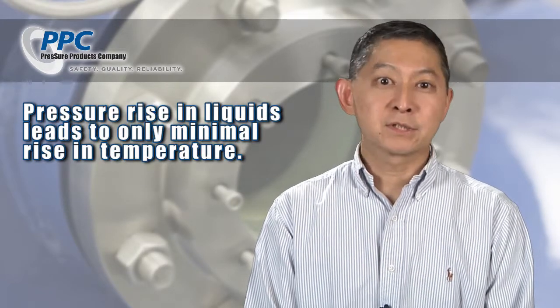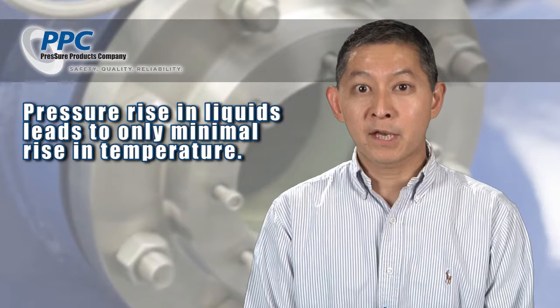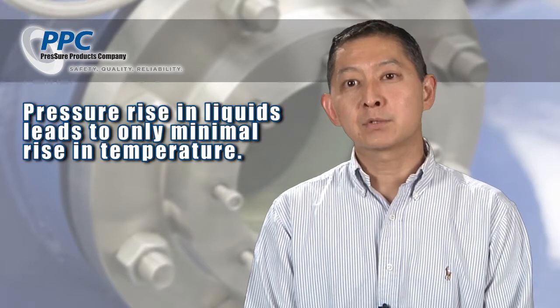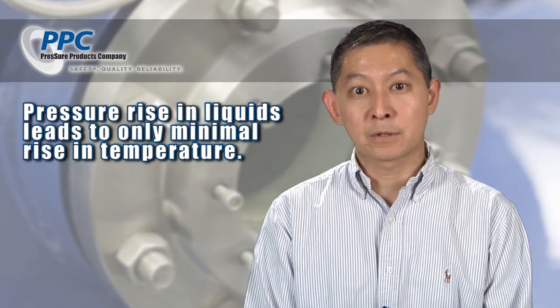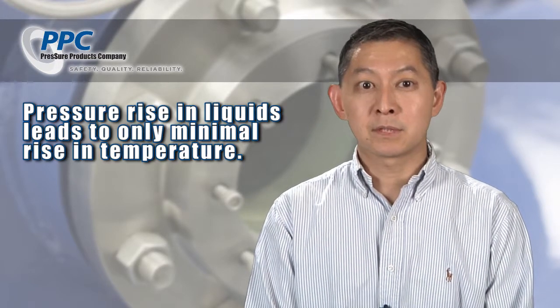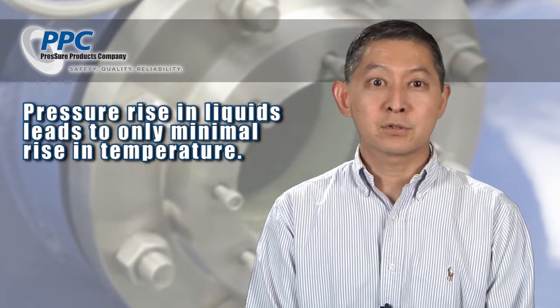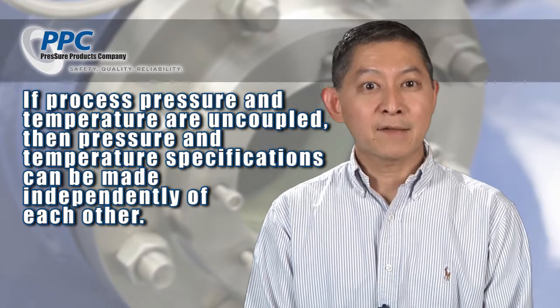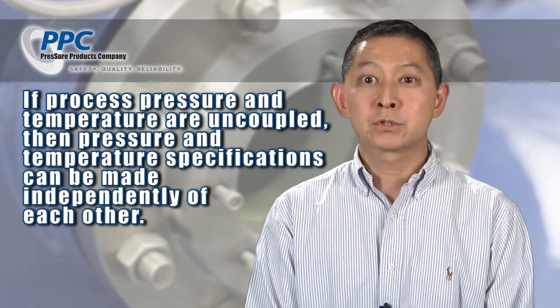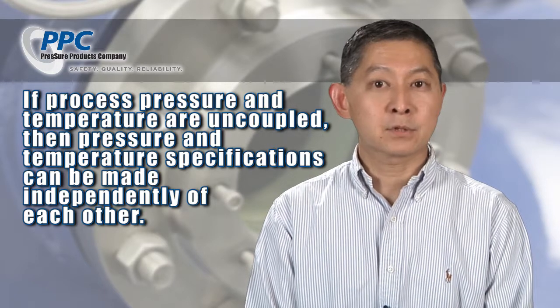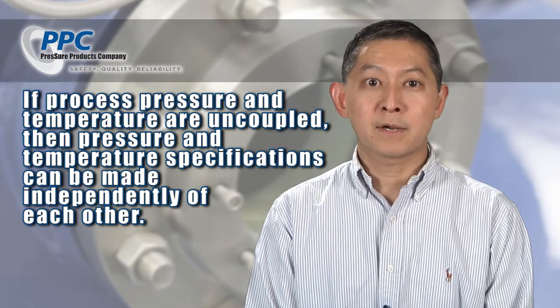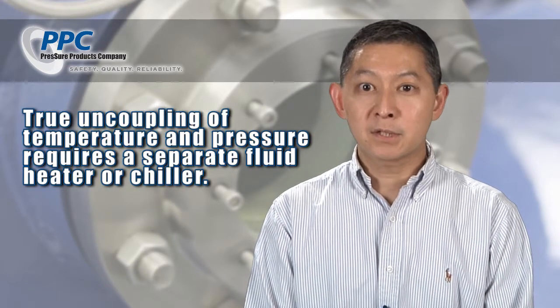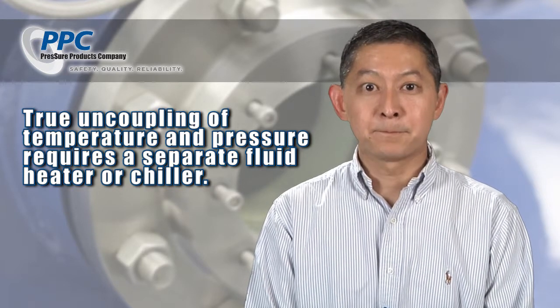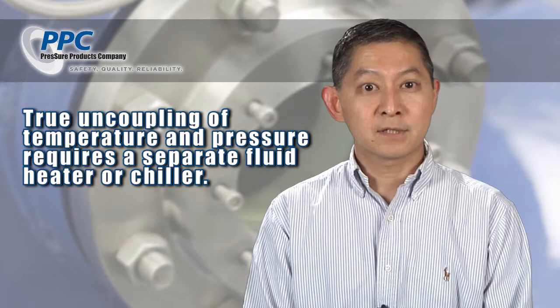Now, that total absence of safety margin on the temperature scale is generally okay for liquid processes. Pressurizing liquids to 150 psi is hardly going to raise their temperature. In fact, pressurizing even to 600 psi will raise the temperature very modestly. Also, if the fluid pressure and temperature are truly decoupled, not having a temperature margin of safety would be okay. So if you have a process involving very high temperature liquids, like motor oil, and you pressurize that to 150 psi and heat to 450 Fahrenheit in separate steps, a commercially available sight window with those ratings will be fine. In fact, this is how sight windows are generally tested.